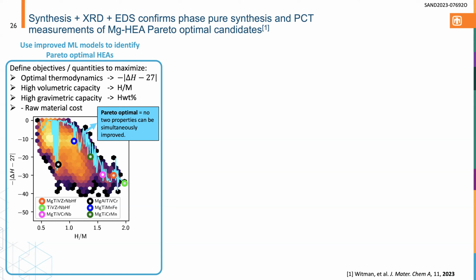materials, right? So I can't show all 4 dimensions on one plot, but if you look in this plot here, I'm showing the enthalpy target and the H to M target. And you can see that, of course, the machine learning captures that as you destabilize the hydride and you get delta H as close to 27 as possible, you lose capacity. Just a well-known and unfortunate physical limitation, but because you can formulate the problem this way, you can identify the Pareto optimal materials. So that's all the materials on this graph, essentially, in which no 2 properties can simultaneously be improved by switching to another material.